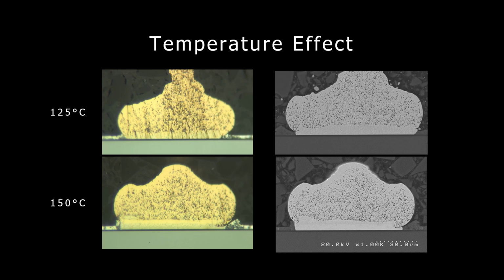These are ball bonds from plastic encapsulated devices that have been stored for 1,000 hours at high temperature. This has caused the intermetallic region to expand. The higher the temperature, the greater the expansion.